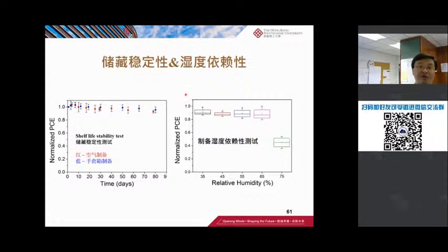Although I'm fabricating this one in high humidity, 55%, we actually see the stability of this device is good if I'm using fast enough blowing. I assume that when we're doing that nitrogen blow, you actually avoid the water penetrating and destroying your device.